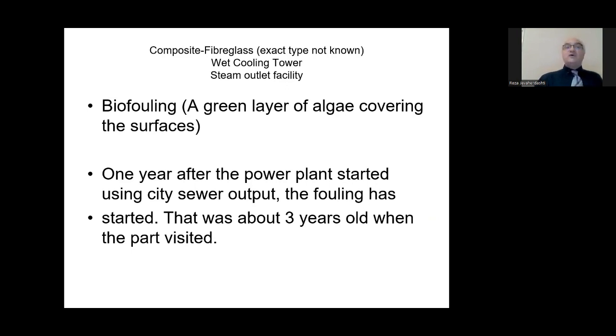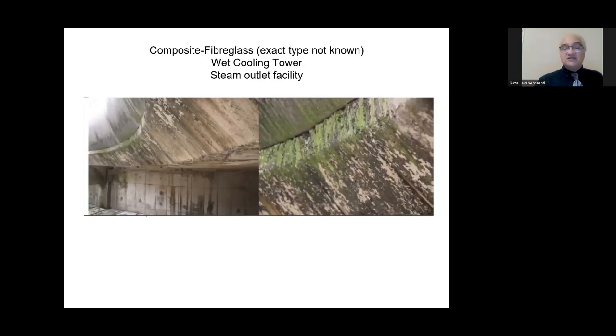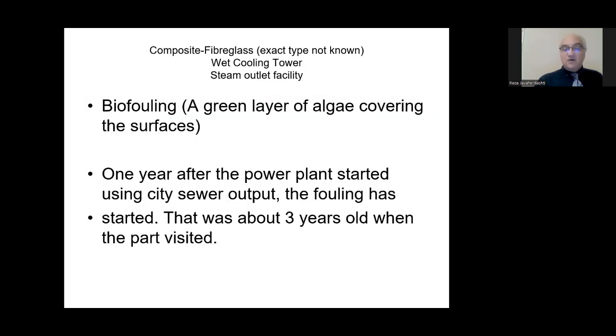In some countries where there is water deficiency, they prefer to take the city sewer water, treat it chemically, and then use it as processed water. If the treatment is insufficient, you will end up with cases such as this. And this happened almost 1 year after the change. The picture that I took was after 3 years, when the plant had shifted from using well water to municipality sewer water.